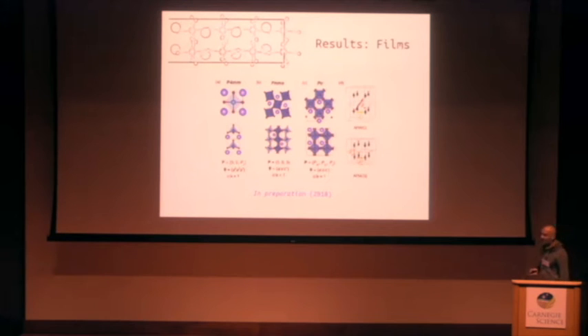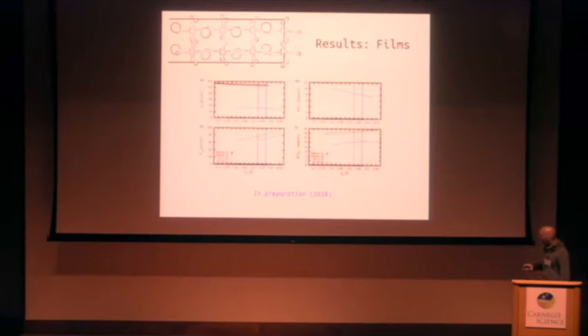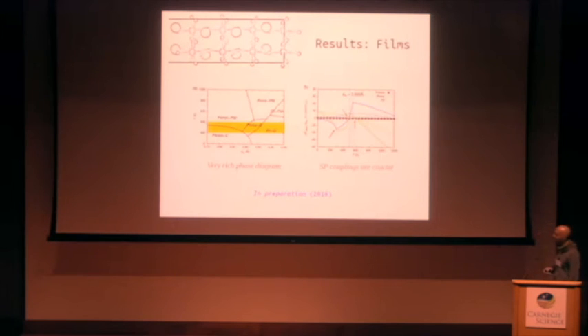In this case, however, the c/a ratio is quite close to 1. So here is the evolution of the polarization in plane and out of plane, and also of the oxygen octahedra. As you can see, the polarizations of the monoclinic Pc phase and the P4mm are quite large, right? So we did exactly the same as we did in the bulk case. Now we calculated the Gibbs free energy for the three different polymorphs that appear at zero temperature, and saw how, as you increase temperature and the magnetic moment and everything changes,